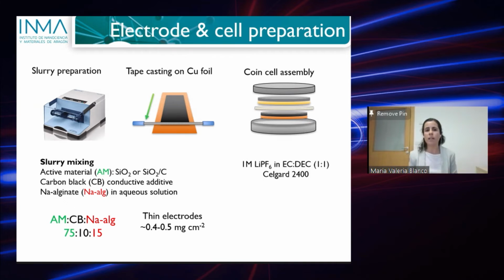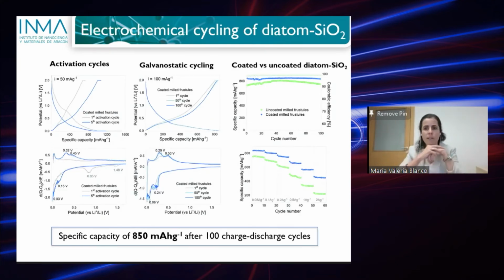And then we casted this slurry on top of a copper foil using the Dr. Blade method, and then we punched out the disk of electrode, and then we assembled it in coin cell using some standard electrolyte, that is LiPF6, and we made some coin cells to do the electrochemical tests. So the first results we got using this new material that comes from a natural feedstock are in this slide.